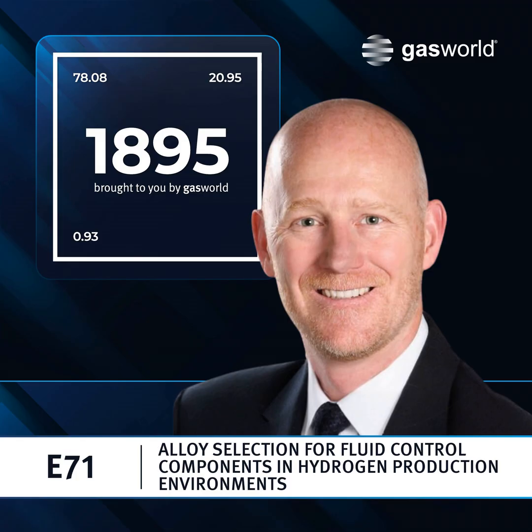Right, yeah, so it's probably worthwhile to just do a brief explanation of the process as we go through. I think many of your listeners may know something about this, but SMR, as you mentioned, uses methane, or the methane in natural gas, along with a catalyst and pretty high temperatures on the order of 700 to 1,000 Celsius. And that process generates hydrogen from the methane gas, uses the oxygen in the system to break the carbon and hydrogen bonds. And one of the products that evolves in this process is carbon dioxide. That can be captured and sequestered, which helps reduce environmental impacts, but of course increases cost.